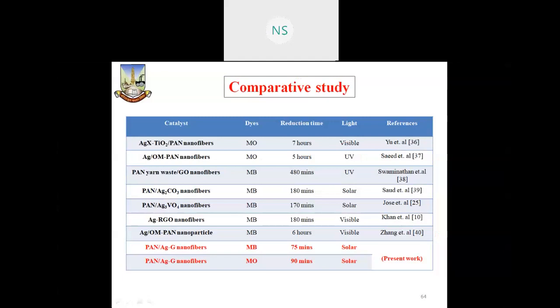So this is the comparative study. The fiber we used is PAN Ag graphite nanofiber for methylene blue. Time required for degradation is 75 minutes under solar light. This is the present work. And PAN Ag nanofiber for methyl orange takes 90 minutes. But the above reported schemes for methyl orange and methylene blue require 7 hours, 5 hours, 480 minutes, 180 minutes, 170 minutes, 6 hours. We require only 75 minutes and 90 minutes for methylene blue and methyl orange, respectively. Next.